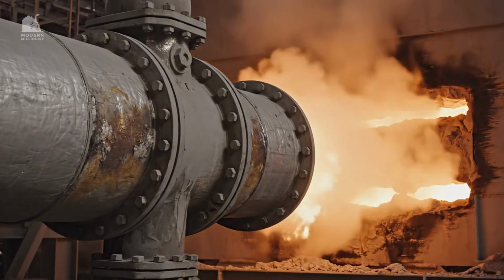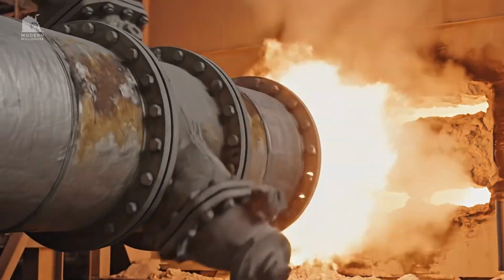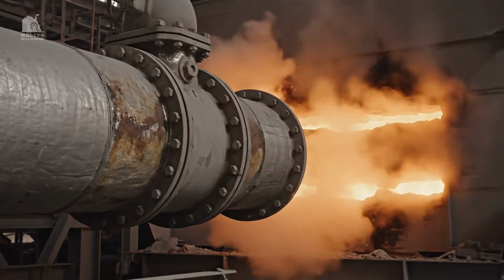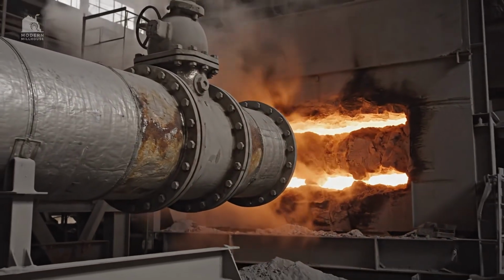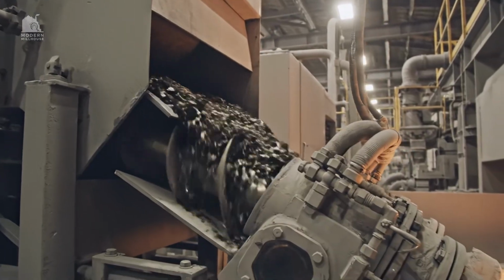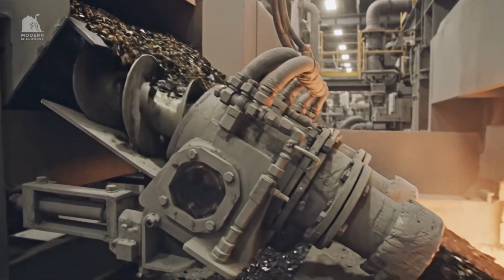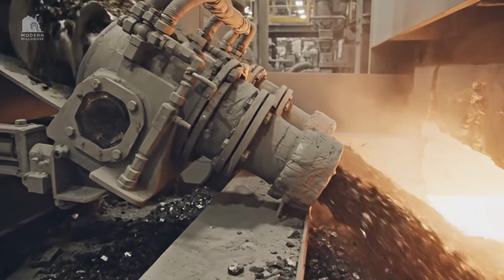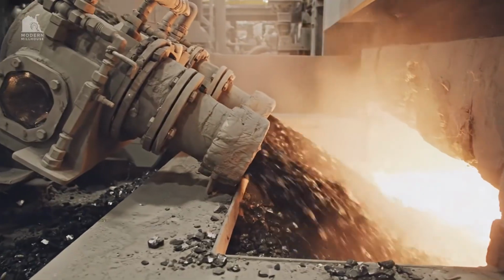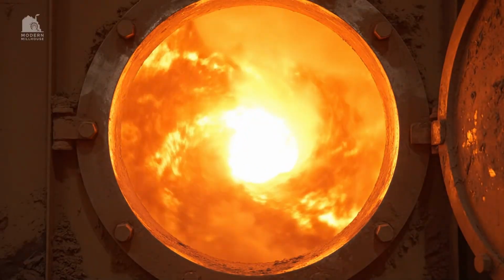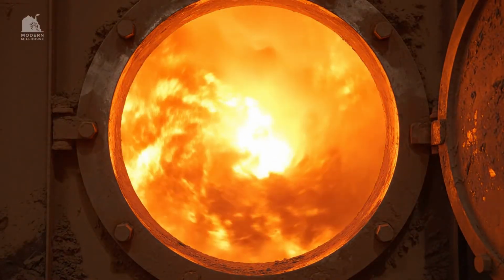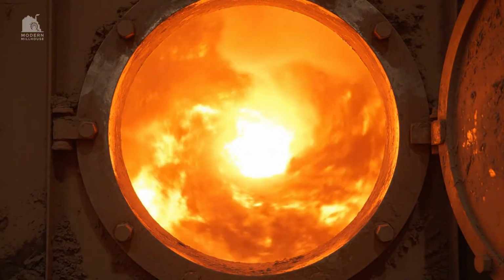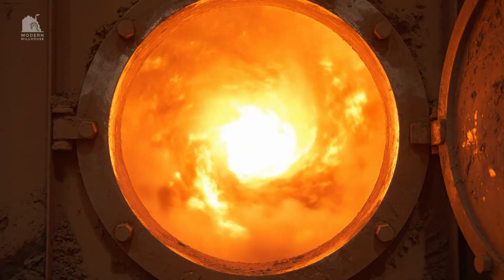Hot air recovered from the clinker cooler supplies oxygen and heat to the calciner, improving overall efficiency. Plants may burn coal, petcoke, or alternative fuels, but combustion must be stable to protect clinker quality. At roughly 600 to 900 degrees Celsius, calcination accelerates and CO₂ begins releasing rapidly.